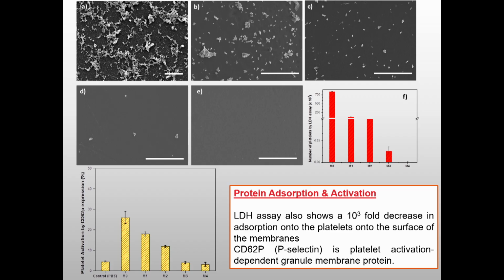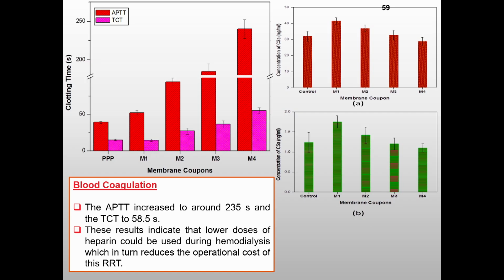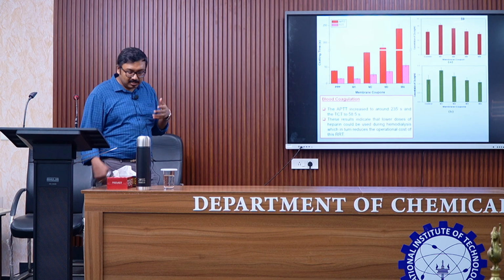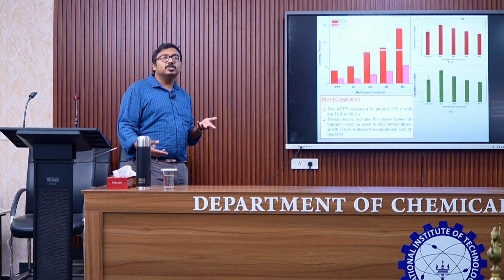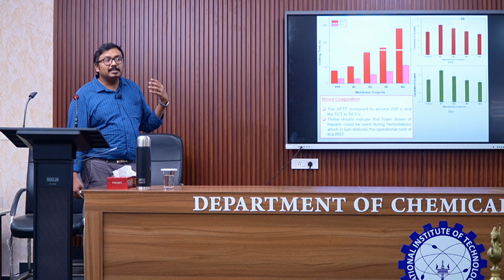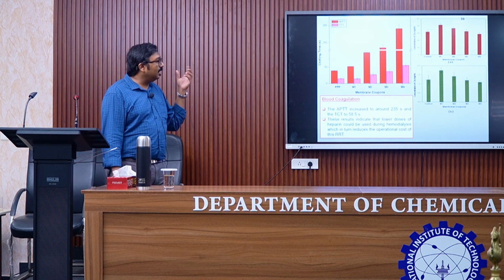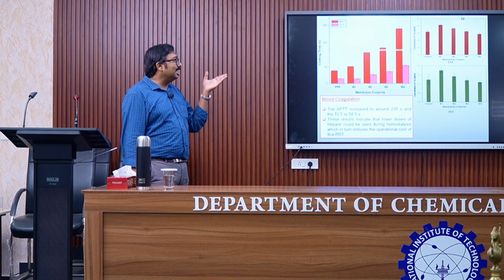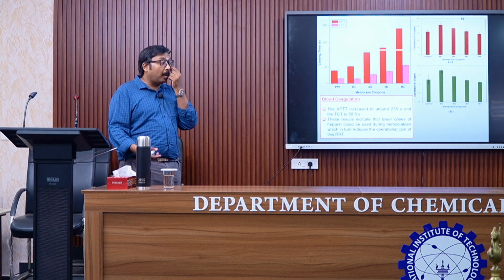Again, we have done all the same kinds of biocompatibility assays. And here the interesting thing is the clotting time. Previously there was no significant increase in clotting time, or it just doubled from 40 seconds to 80 seconds. Here you could see that from around 37 seconds, the clotting time has reached around 250 seconds. Heparin is a well-known anticoagulant, used to prevent clotting during surgery. When we immobilized it on our membranes, we saw that the heparin was still active, and it can still impart its properties.